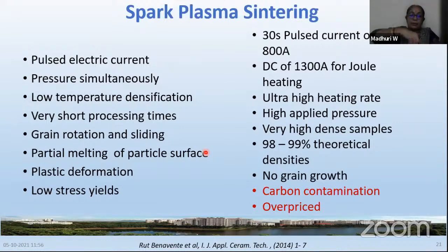So in the graphite mold, a high pressure is simultaneously given, and there won't be much heat, but because of pressure and the high electric pulse which is being passed, the pulse is really very, very large. You can see here it's 800 amperes. 800 amperes is a very large current, and to keep the Joule heating there, you will be using a DC power supply of approximately 1300 amperes. That is a very huge amount of electric current, though it's for a very short interval of time. It's a very, very high current.